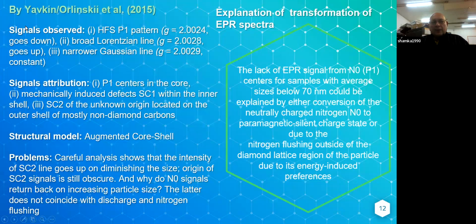The explanation of another group, the Yavkin and Orlinsky group, which got the same experimental set of data, the same signals, but slightly different attribution. Again, P1 centers in the core, a broad line due to mechanically induced defects in the shell. And the third signal, they said, is due to unknown centers located in the outer shell of mostly non-diamond carbons. Unfortunately, this is again core shell, but with a very strange explanation of the third signal.